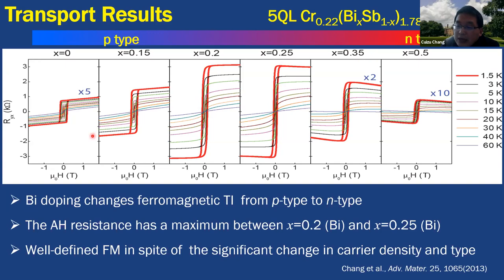We can see that unlike the diluted magnetic semiconductor, like manganese-doped gallium arsenide, when you tune this kind of carrier type, the ferromagnetism is always here. And we can realize the ferromagnetism in P-type and N-type, and also in this kind of insulating regime between 0.2 and 0.25.